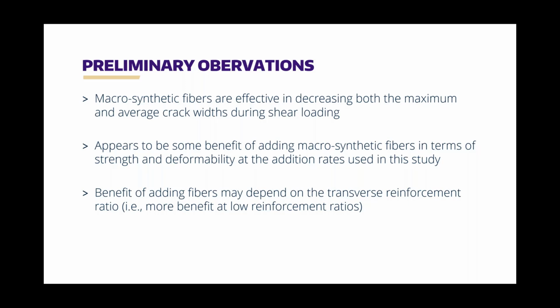So again, we're still processing the data, and we're still digesting what we're seeing out of it. But I think some of the preliminary observations here is that macrosynthetic fibers are effective at decreasing both the maximum and average crack widths during shear loading. That's sort of what we would expect and what we're hoping to see.